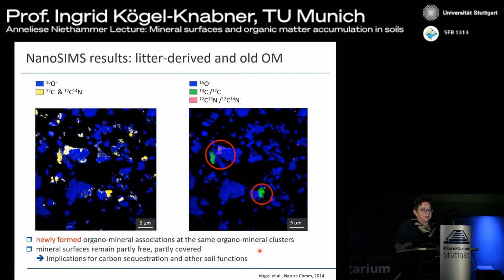And if we also find 15N, this is always because the nitrogen generally goes through the microbial biomass. This is always a hint that the microbial biomass is really relevant here and is part of this accumulation. But of course, we did a lot of sample preparation and we disturbed the initial structure, but still we see that we have these mineral surfaces that remain partly free and are only partly covered.